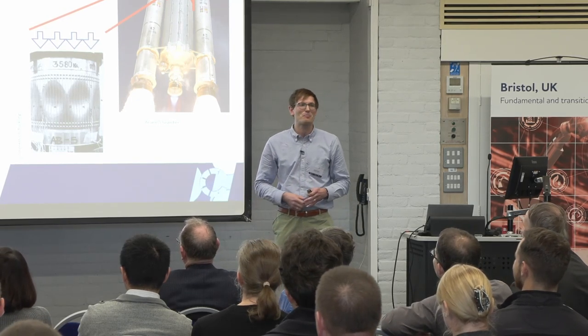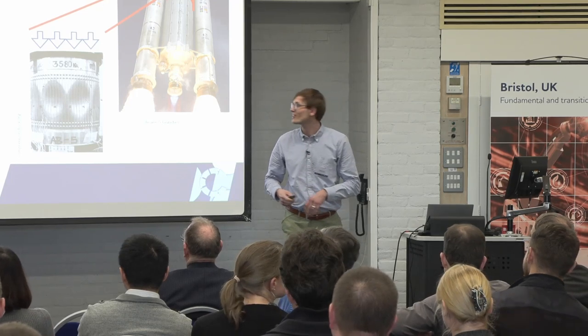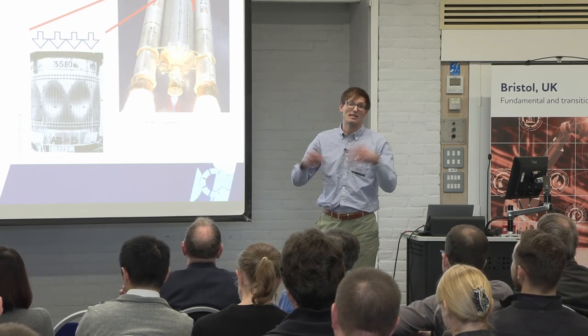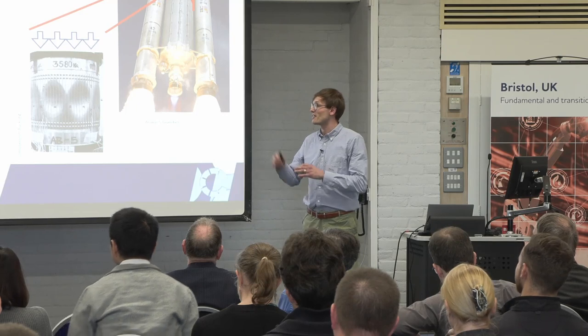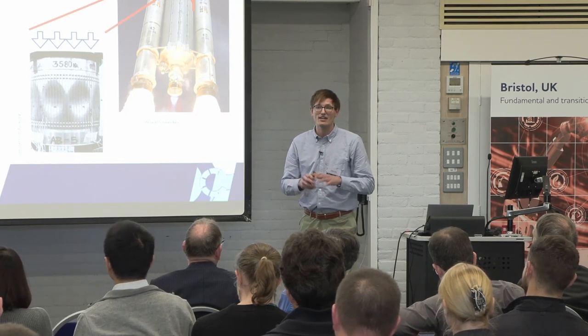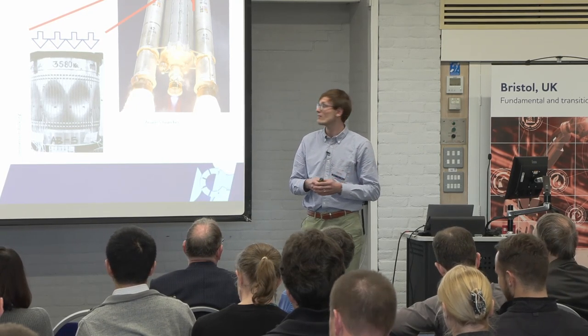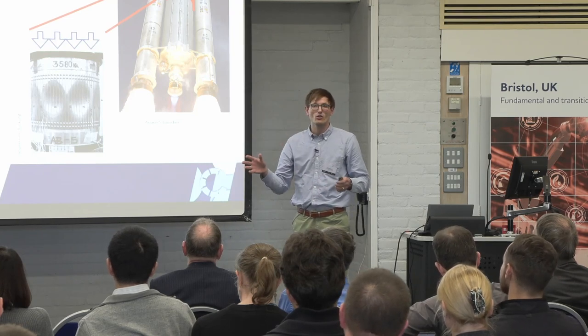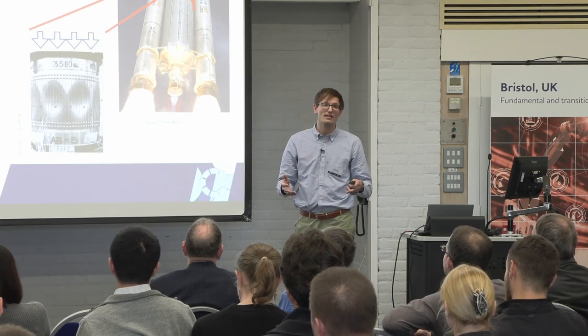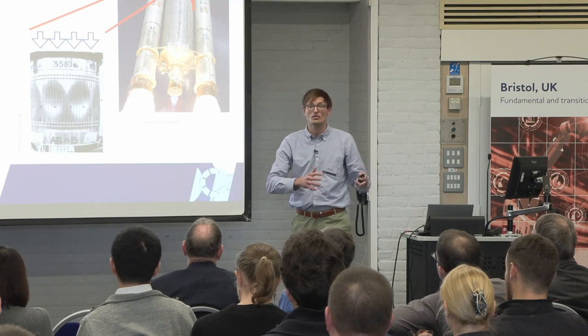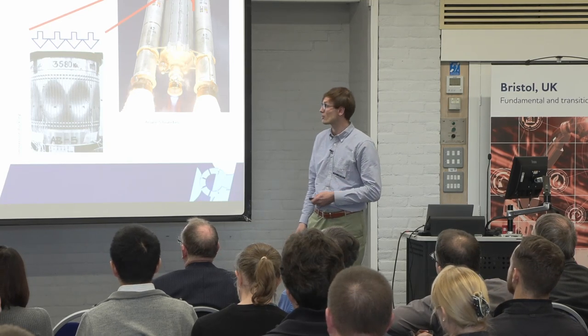Now, one of the biggest headaches over the last couple of years, or in general, is that these structures are very, very sensitive to any form of geometric imperfection. So even if you have an undulation in your wall, a fraction of the wall thickness, you can dramatically reduce the expected buckling load of these structures.